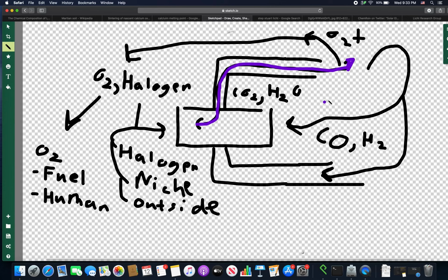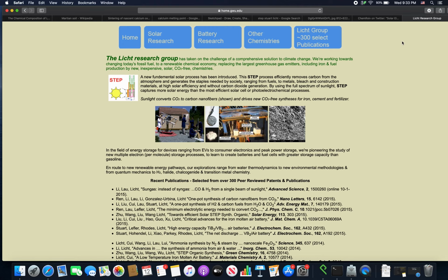Now, how do we split it up? Well, I'll put some link there, but this research group that I've helped work with has invented the STEP process. And what the STEP process does is it can really, really efficiently split a bunch of molecules, including calcium carbonate and make lime. It can make carbon nanotubes out of CO2. It can make iron out of iron oxide. It can make aluminum out of aluminum oxide.